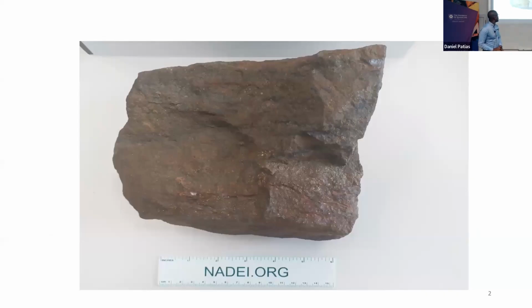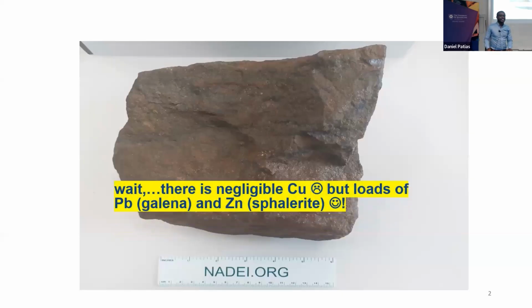So this is a low-grade ore material that I received during the early hours of my PhD work at the University of Melbourne. And I did 4 months of characterization, so doing SEM, EPMA, thin sectioning and the likes, XRD, XRF. Unfortunately, after 4 months of hard work, there was very negligible copper, and loads of galena and sphalerite. So that sort of motivated us to develop, combining geochem and hydromet, new ways to extract copper, but then considering energy consumption for grinding as well as water use.